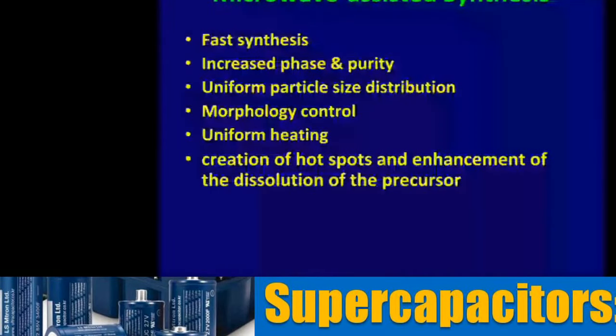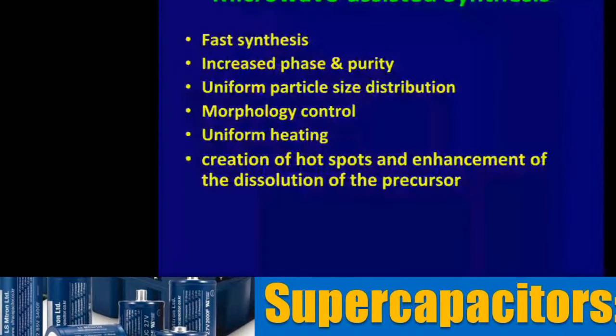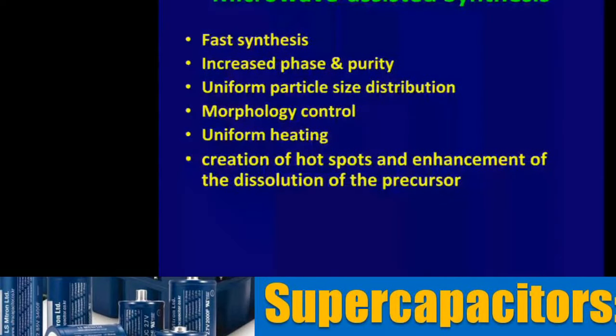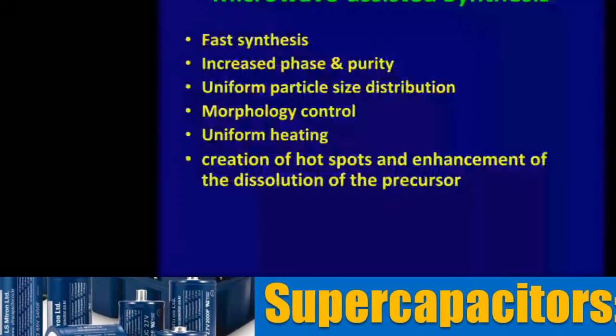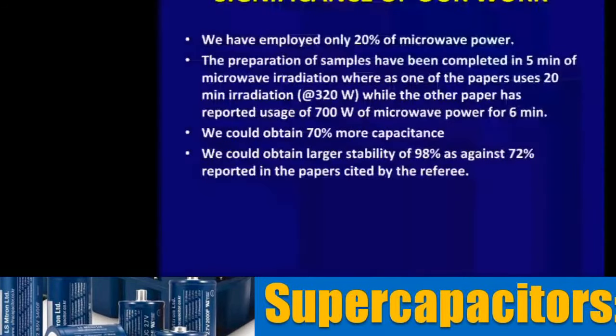In our methodology, we used a very simple 800 watt microwave oven meant for home use. In 5 minutes of use, it yields excellent material. I request all people to try this if they wish to, because it's one of the easiest methodologies. And the microwave oven is available for about 6,000 to 7,000 rupees. The significance is that we have used very little power.